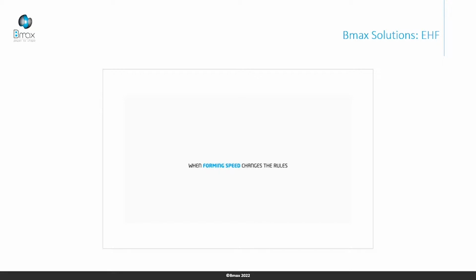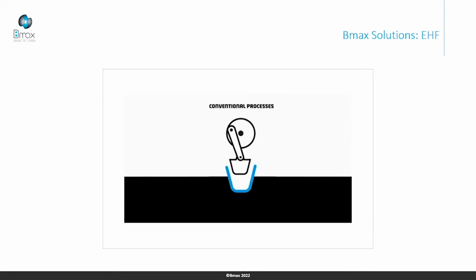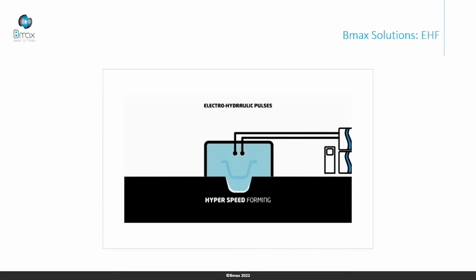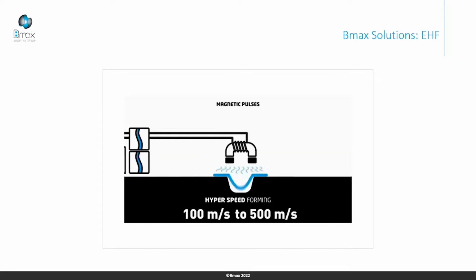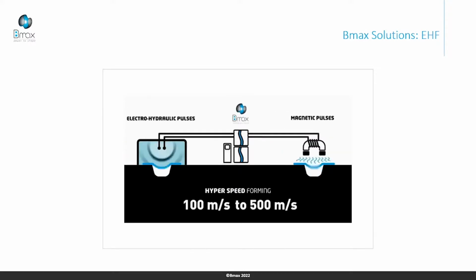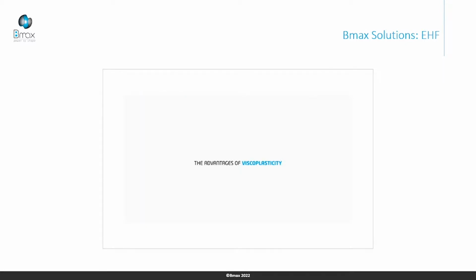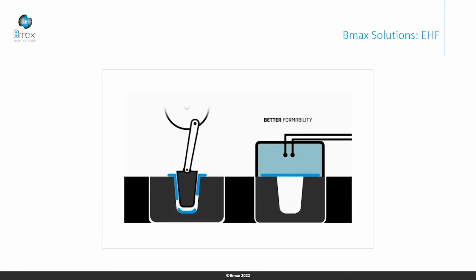The main advantage of EHF, like MPF, is the speed of the process. It's a dynamic process. Compared to conventional forming processes, where the speed is comprised between 0.1 millimeter and 10 meters per second, the speed in EHF can reach 100 meters per second, and in MPF up to 500 meters per second. So with this speed, we can change the structural response and material behavior. It's viscoplasticity. In this way, we can enhance the formability compared to conventional processes.